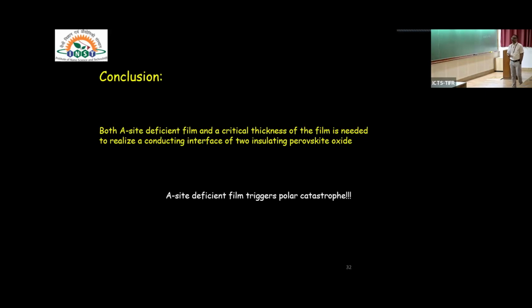So what we conclude is the following: both an A-site deficient film and the critical thickness of the film are needed to realize the conducting interface of two insulating perovskite oxides. So we believe that an A-site deficient film triggers the polar catastrophe. That is what we believe. We don't know if it is true or not, there could be something more, because as Tanuja was mentioning, for gadolinium titanate, people could see this for 1 monolayer of thin film only.